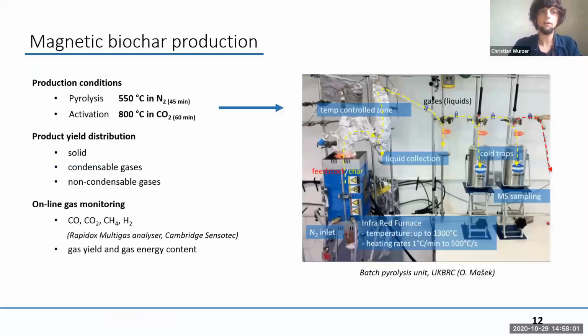And then we pyrolyzed it at 550 degrees in nitrogen, followed by a two-step activation at 800 degrees in CO2. And then we analyzed the product yield distribution, so solid, liquid, and gas fraction. Additionally, we also used online gas monitoring to analyze the composition of the gas fraction, so for CO, CO2, CH4, and H2, which is sufficient to calculate the gas energy content to know if we can utilize this fraction for a more efficient pyrolysis process.